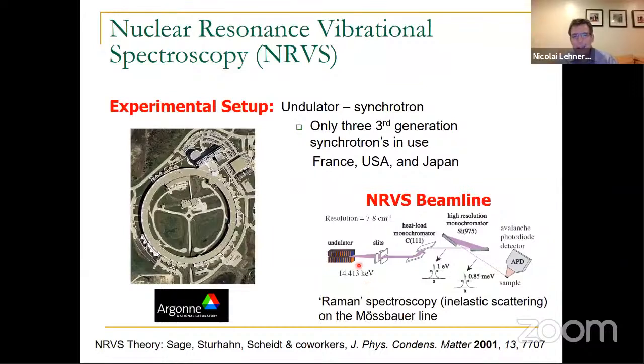You can see here at the beamline, this is a very complicated setup where the beamline itself produces the X-rays, but they have a high intensity and they are also not monochromatic. Then at Argonne National Lab, at the APS, they built this monochromator system that allows you to get down to a resolution of about 1 millielectron volt. And that's about 8 wave numbers. You can see it's a little bit better than this. So our resolution is about 6 wave numbers with this experiment.